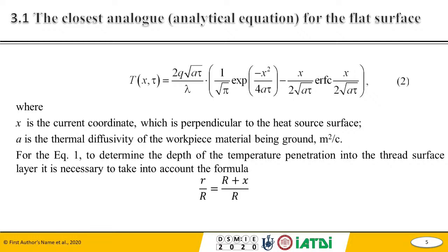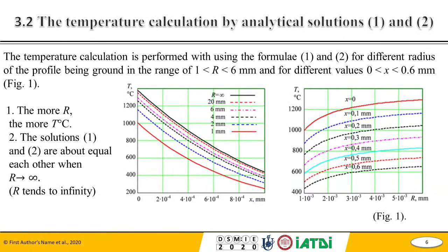Next slide is number 6. This slide shows the temperature calculation by analytical solutions 1 and 2. The temperature calculation is performed using the formulae 1 and 2 for different radius of the profile being ground in the range from 1 to 6 millimeters, and for different values of x from 0 to 0.6 millimeters. Conclusion: first, the more radius, the more grinding temperature in degrees Celsius. And second, the solutions 1 and 2 are about equal to each other when radius tends to infinity. The next slide is 7.